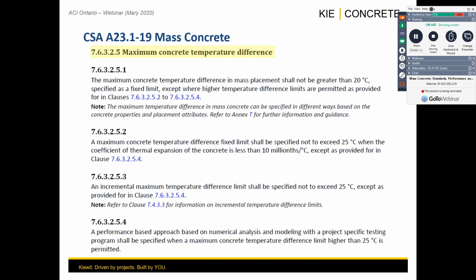appropriate properties. So in that case, based on a numerical model analysis for a specific project, a maximum concrete temperature difference limit higher than 25 degrees Celsius is permitted. So if you want to go above 25 degrees Celsius temperature difference limits, the standard tells you that you need to go through analysis and testing with the performance-based approach.